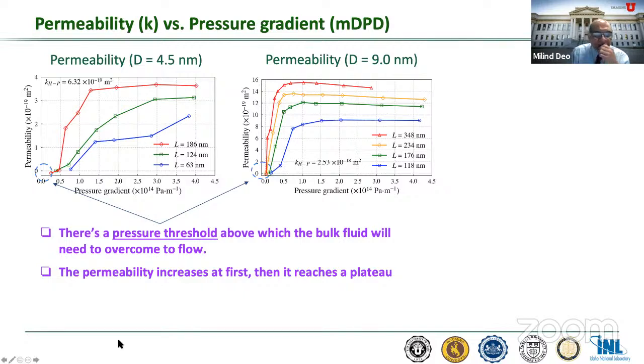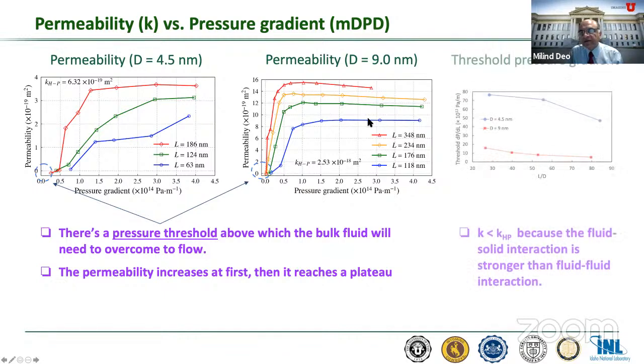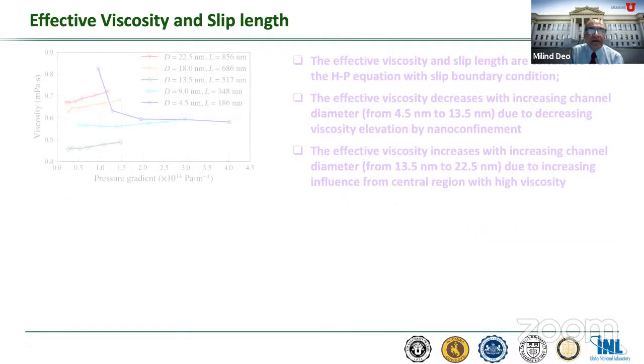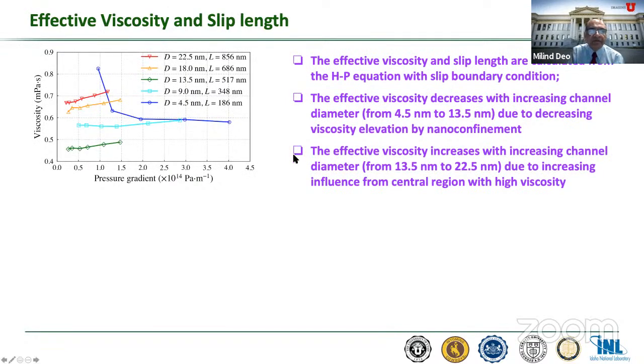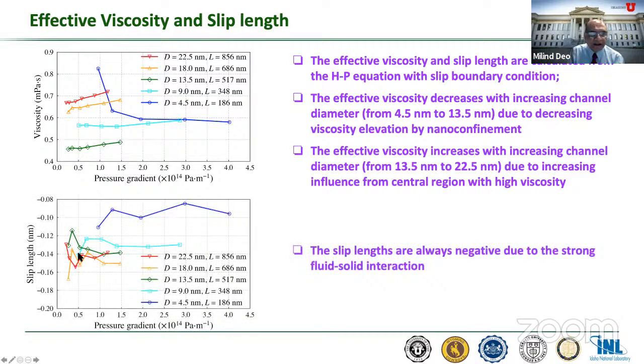On the permeability side, we do see that a pressure threshold needs to be satisfied before the fluid will actually enter the system, and the permeability increases first and then reaches a plateau. And the more important thing is that in most of the simulations we saw flow reduction instead of enhancement. And the slip length in most of these cases tends to be negative, not positive like we had seen for carbon nanotubes.